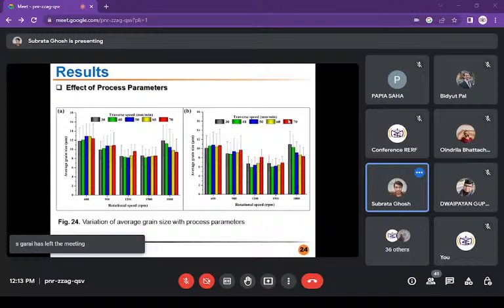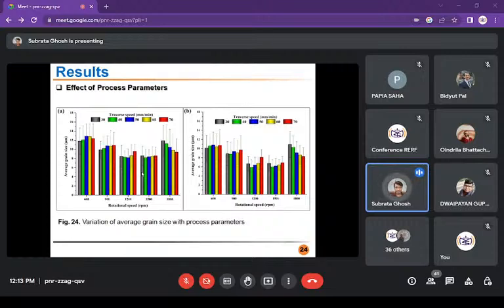Okay, and this is the graph of average grain size with respect to rotational speed. Here, one beautiful thing is that at 600 RPM you are getting a very good grain size. Because of this, the heat generation plays a very important role. Because of the temperature, grain reorientation will always be happening. Because of that only, the average grain size varies with the rotational speed.